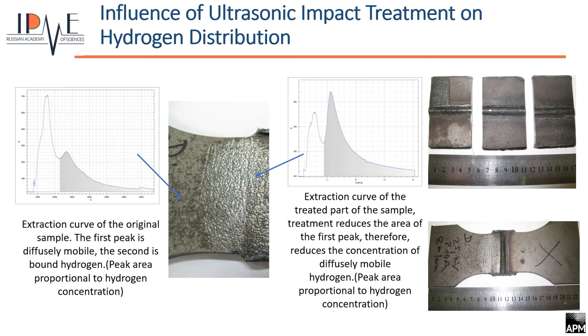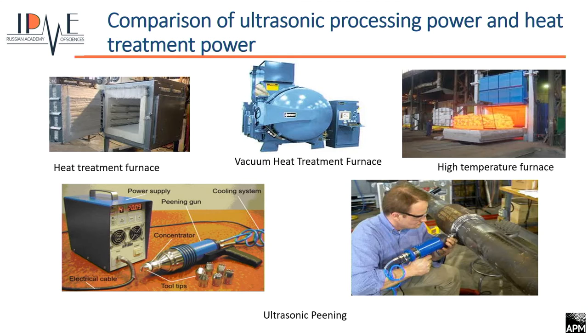We treat the surface by ultrasonic shot peening, and after that we measure the hydrogen concentration. Before treatment we have a great hydrogen concentration, the square under this curve is the proportion of the concentration of hydrogen. And after treatment, it is four times smaller. So the surface effect may be used in engineering application in industry for very effective increasing of the mechanical property.